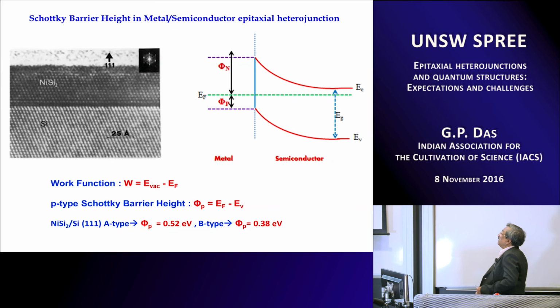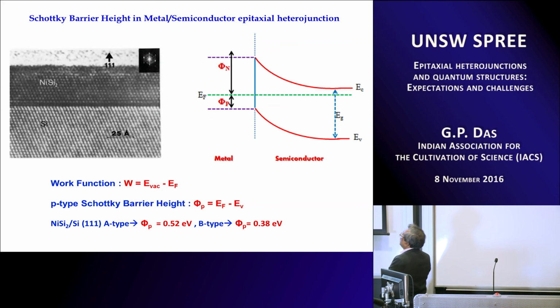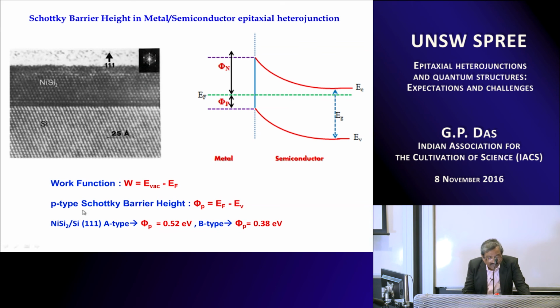Let's look at this cross-sectional TEM picture of the epitaxial interface between nickel disilicide and silicon. See, this is silicon 111 and this is nickel disilicide and this is the interface, and it is interesting that silicon and nickel disilicide have almost the same lattice constant. One is a metal and the other is a semiconductor. So this particular interface is responsible for the Schottky barrier height. And here this band diagram shows you there is a Fermi level on the metallic side and there is a conduction band and valence band.